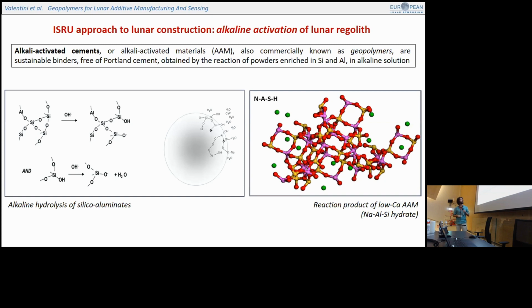Okay, so we start from different kinds of aluminum silicate powders, and by using an alkaline solution, we can induce, as you can see on this side here, basically the polymerization of the aluminum silicate network, dissolution of the powder, and when the solution becomes supersaturated enough, we induce the formation of these reaction products called NASH because it's sodium aluminum silicate hydrate, which is the product that gives cohesive properties to the material. Okay, so this kind of alkali activated materials are also known as geopolymers.